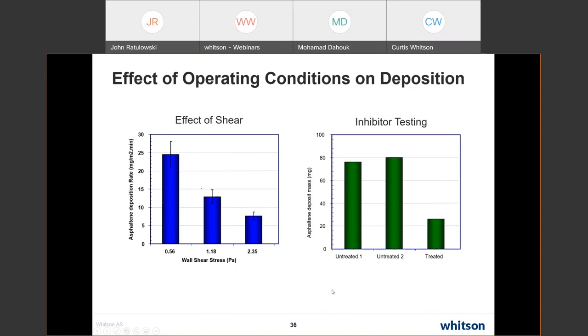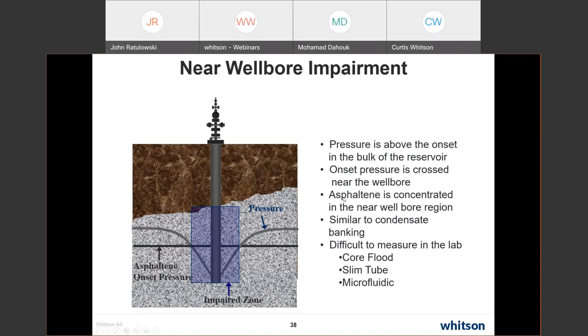All right, so finally, just a couple words about near wellbore impairment. This is a real problem. If the pressure in the reservoir is above the onset pressure, and in the area near the well where we draw it down, it falls below the onset pressure, we can get an accumulation of asphaltenes in the near wellbore region. It's similar to condensate banking. I keep bringing in fresh fluid and it keeps dropping its asphaltene in this area.